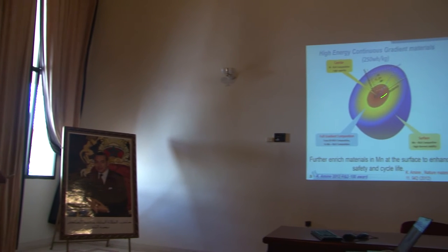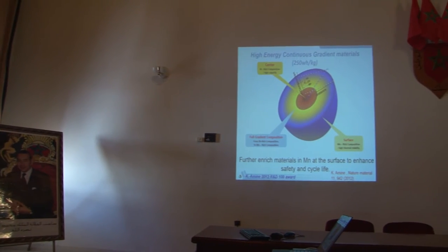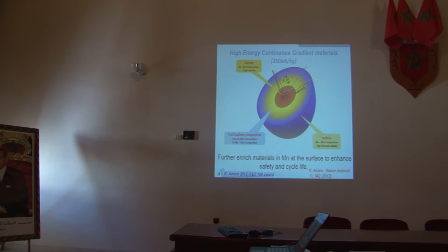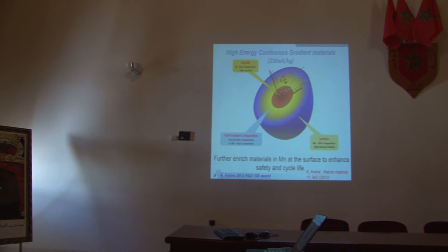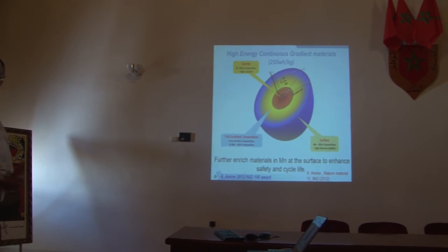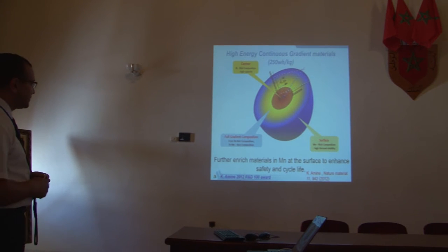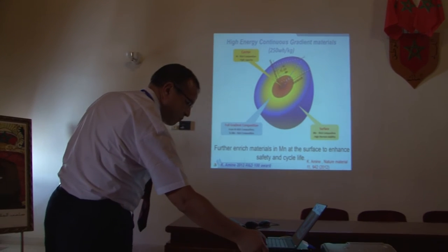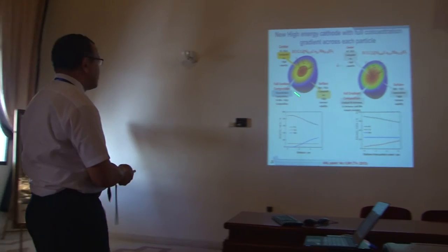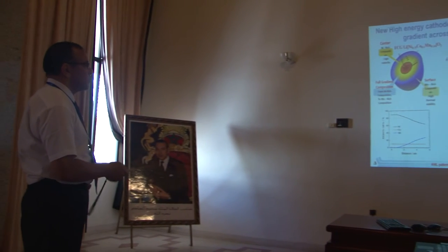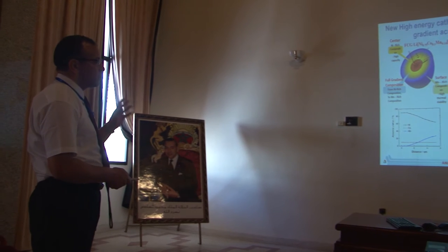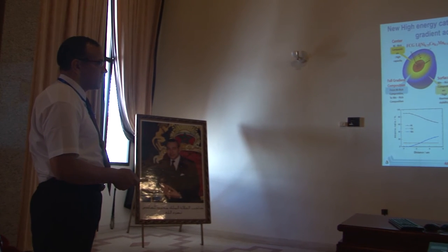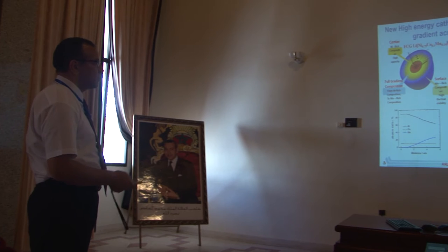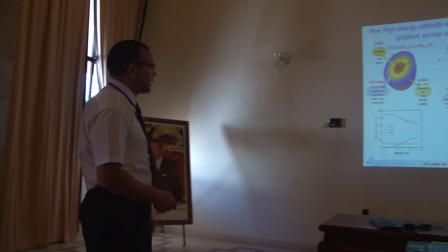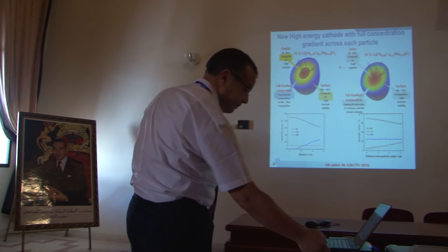Basically, what you do is start higher in nickel at the bulk, and you drop it and increase the manganese. So now you have very high surface manganese that can give you very good stability. Blue means stable, again reducing surface reactivity with the electrolyte and also improving safety. You can do many scenarios. This is the first one, which has full gradient. To enhance the stability across the particle, you can also keep your manganese stable across the particle, reduce the nickel and increase the cobalt. So you have many, many scenarios. Argonne has had a patent on this since 2013.